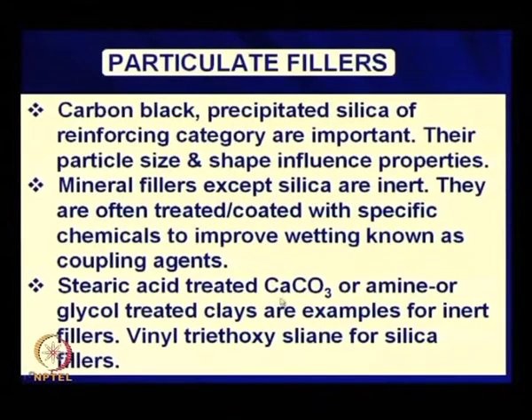Now, that can be improved if you can give a very thin coating to the filler particle. Here is an example of stearic acid treated calcium carbonate. Calcium carbonate is an inert filler, but you can easily disperse it in a hydrocarbon or an organic polymer more easily if you can make a thin coating of organic material. Stearic acid, you know, stearic acid, fatty acid.